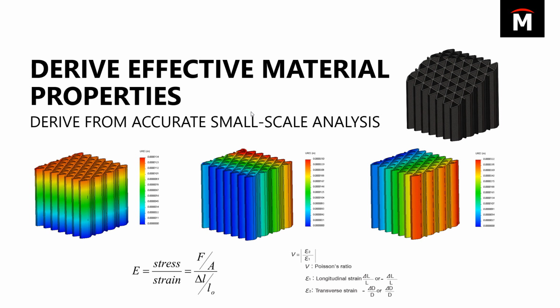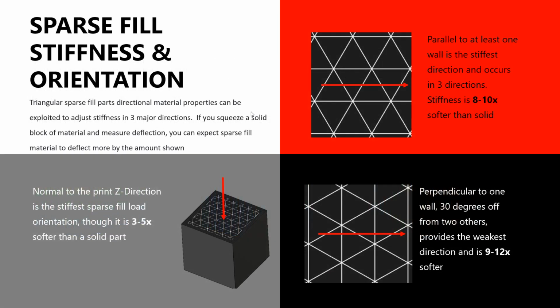The problem was, if you derive the effective material properties from a little sub-study, you create a little mesh and analyze the mesh, and you say, okay, in this direction it's this stiff or that stiff, and that's an equivalent elastic modulus. You end up with material that's less stiff than it should be. So in other words, a 37% sparse fill can be up to 5 times softer than the solid material.